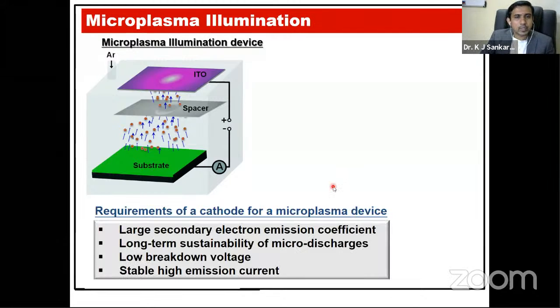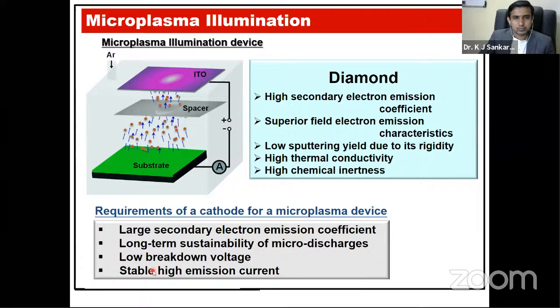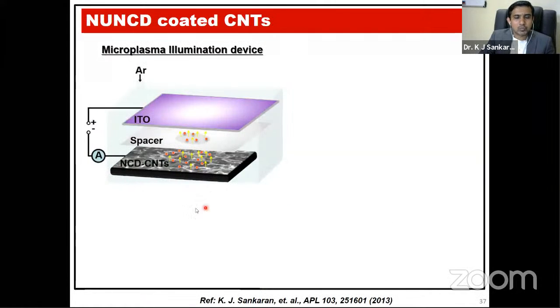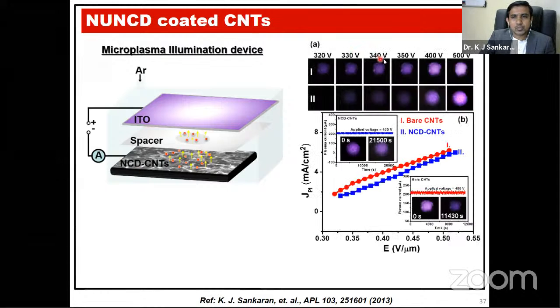As a requirement of a cathode for a microplasma device, it should have a large secondary electron emission coefficient, so it should emit more electrons. It should also sustain micro discharge, with a low breakdown voltage, like a low turn-on field, and a stable high emission current. Why can diamond be used for this microplasma? Diamond has a very good secondary electron emission coefficient. We have already shown superior field electron emission characteristics compared to CNTs and graphene, and a low sputtering yield, because it's the hardest known material, so it has very good rigidity, high thermal conductivity and high chemical inertness.